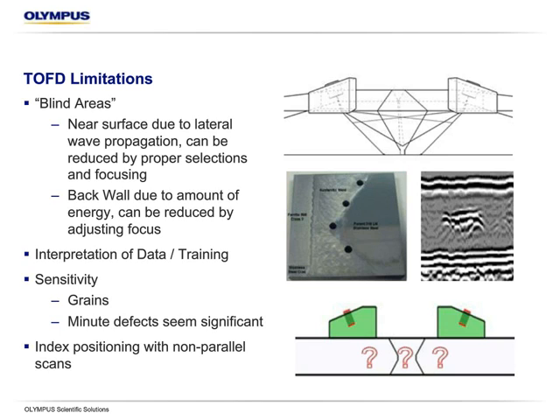This can be reduced by the proper selection of some of those factors, the separation of the transducers, the right frequencies, but it's always going to be there. The other one, known as a blind area, or sometimes called a dead zone, is the back wall. This is typically an area of concern because of the large amount of energy. Again, it's a very flat surface, or a very large surface if it's a pipe. There's a lot of reflected and diffracted energy. This can actually be reduced to be pretty small and actually negligible.